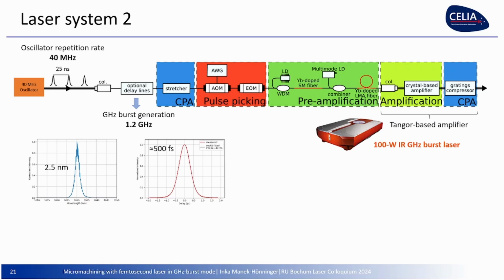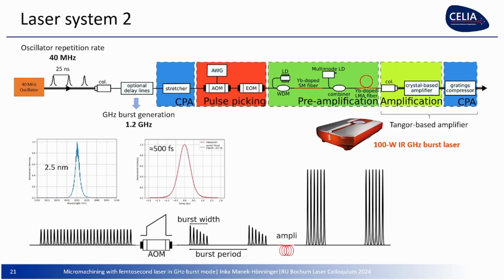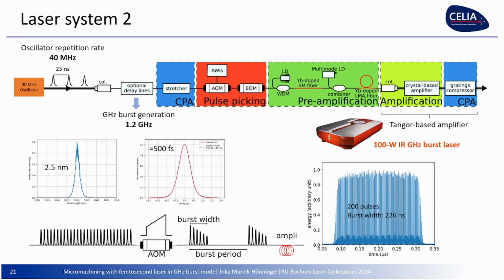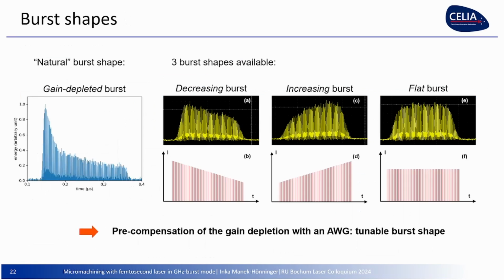And let's have a look at this pulse picking system. There's an arbitrary wave generator, which allows for pre-forming the burst train in order to get flat bursts, and the real bursts are quite flat. What does it mean? A natural burst would have this form due to gain depletion, because at the beginning you amplify much more and then you have less due to gain depletion. So this is the natural burst, and the first experiments were done with the natural shape, gain depleted burst.